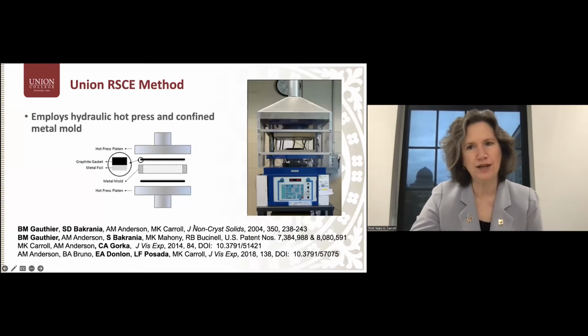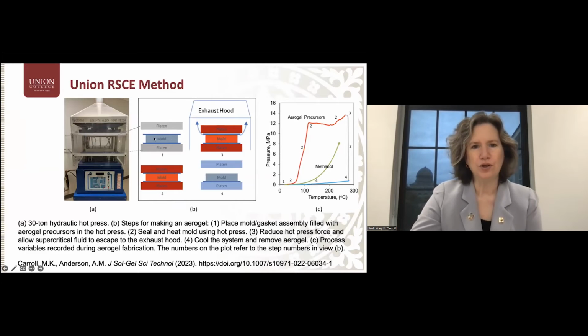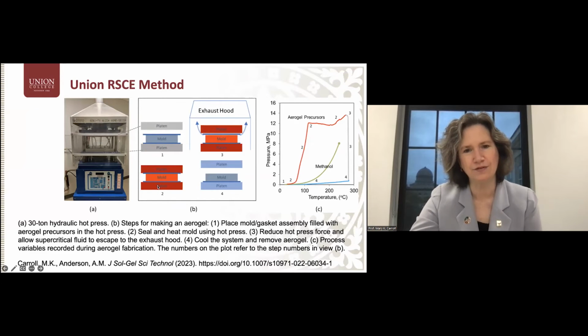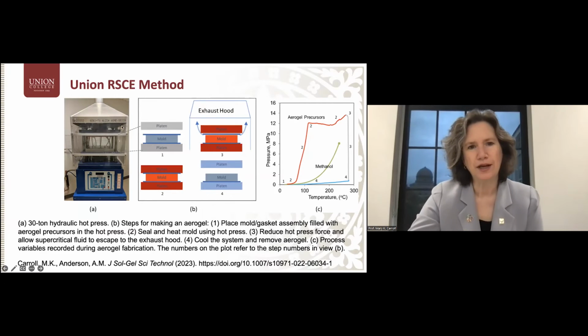We have published and patented, and we have a video article that shows how this method works. We use it to make intact monolithic silica aerogels, although we can also make aerogels of other types. In short, we close the mold in the press. We start to heat the press, which heats the mold because it is made of metal, which increases the temperature of the contents of the mold. And because it is sealed by the pressure of the hydraulic hot press, it can't escape. And this drives up the pressure within the mold.